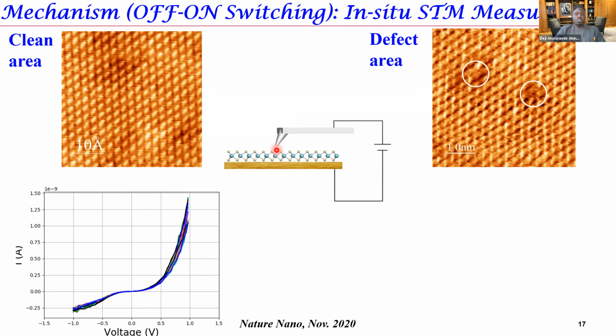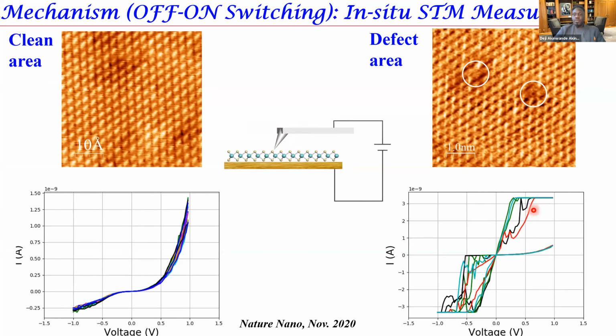So you would normally expect some asymmetry in the IV curves. Then we said, okay, why don't you now put the tip and park it on top of a defect, any defect, and do transport measurements. If you do that, you begin to see the emergence of memory effect. This window in the IV curve is reflective of memristor behavior. So we could conclude that defects, in this case single vacancy or di-vacancy sulfur defects, are essential, but it turns out they are not enough to get the memory effect. You need an additional ingredient.